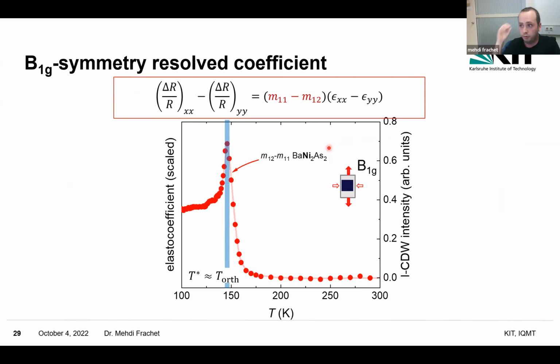Okay, so from the data I just showed you, you can easily extract this M11 minus M12 elastoresistance coefficient. Again, it belongs to this B1g symmetry. So you take just the difference between the two curves I showed you before times some factor. And no surprise, you get this sharp peak close to the orthorhombic transition temperature.